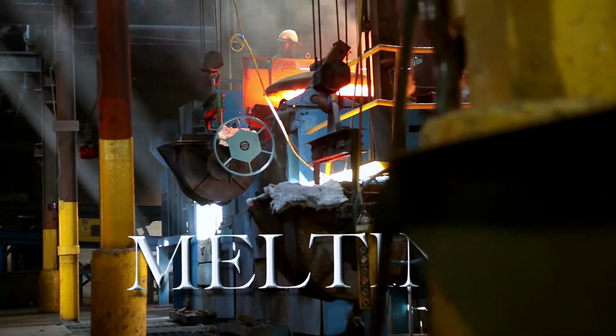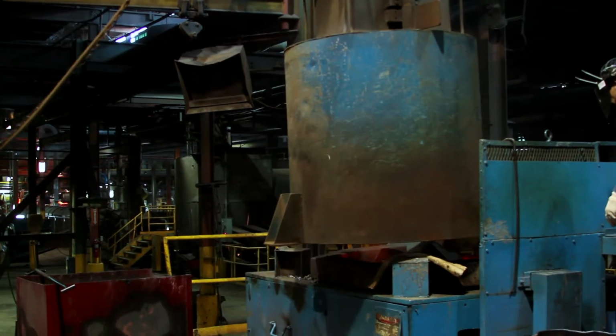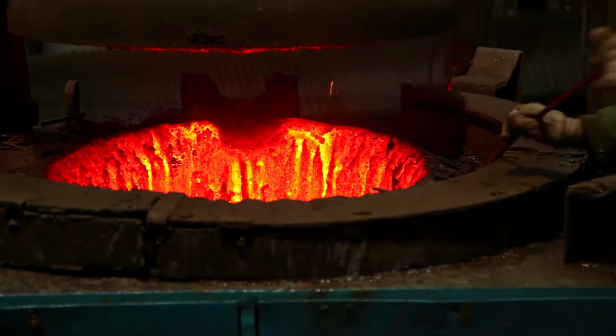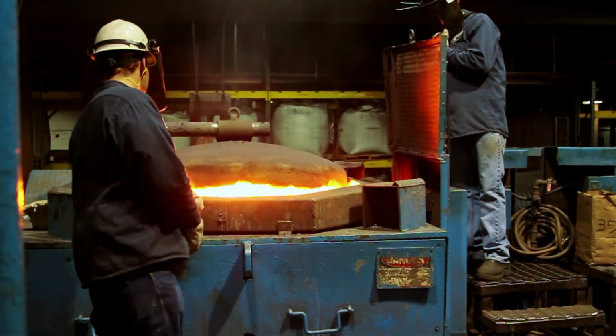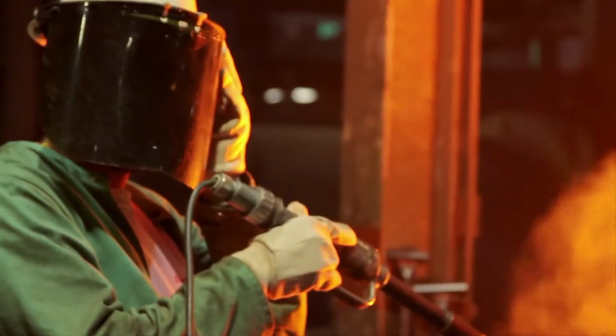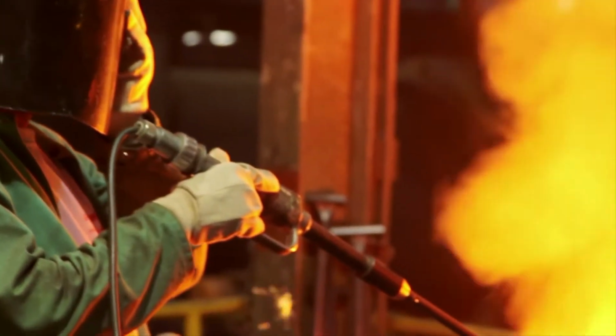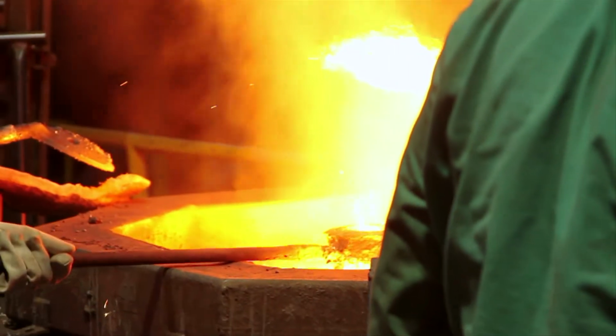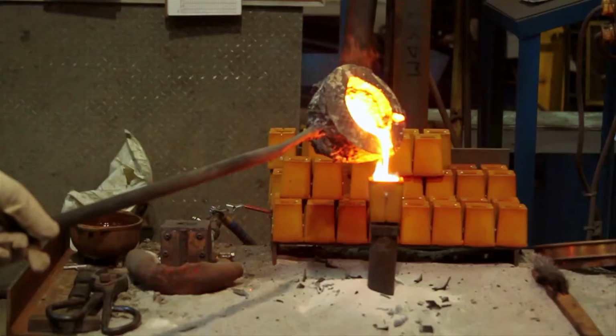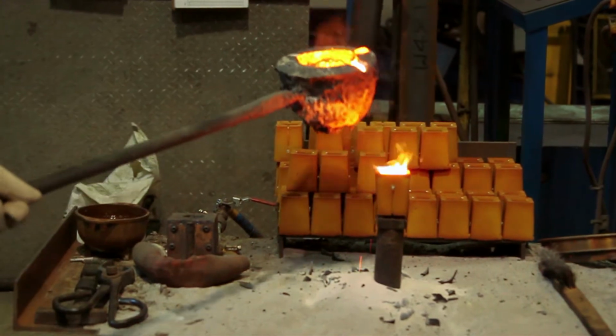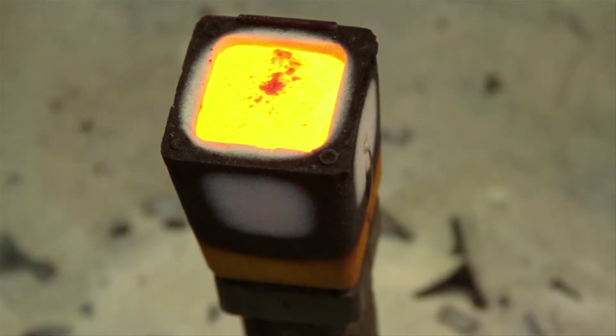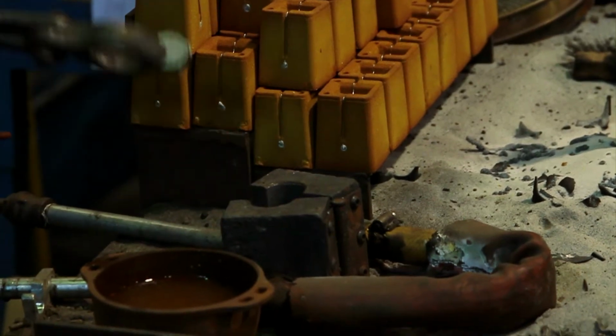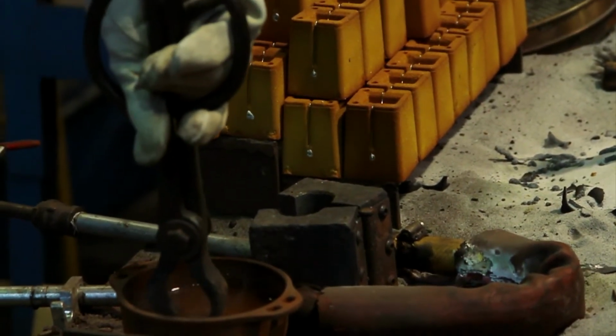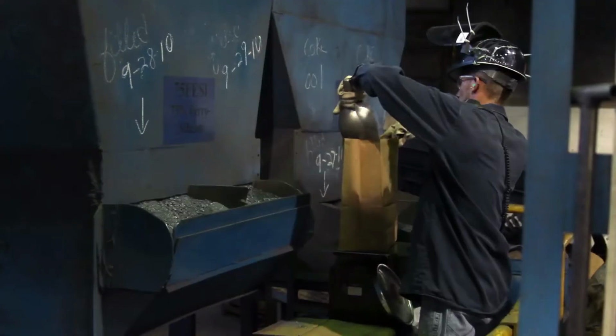This is an electric induction furnace. The furnace runs at 2,800 degrees Fahrenheit and can hold up to 4 tons of molten metal. It takes 15 minutes to melt all the 2,000-pound charge into a super hot liquid metal. It's at this point we take a sample. And depending on the spectrometer results of this sample, workers will add measured amounts of alloys to the iron bath. This is to give our finished pan the specific chemistry to meet our quality standards.